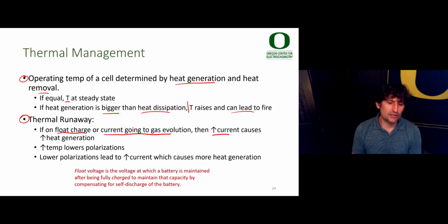That lowers the polarizations because as the temperature goes up, typically conductivities go up and kinetic overpotentials go down. And this can lead to a runaway process where lower polarizations lead to higher current, which causes more heat generation, which continually lowers the polarization. This is called thermal runaway. Define here the float voltage: it is the voltage at which a battery is maintained after being fully charged to maintain that capacity by compensating for the self-discharge of the battery.